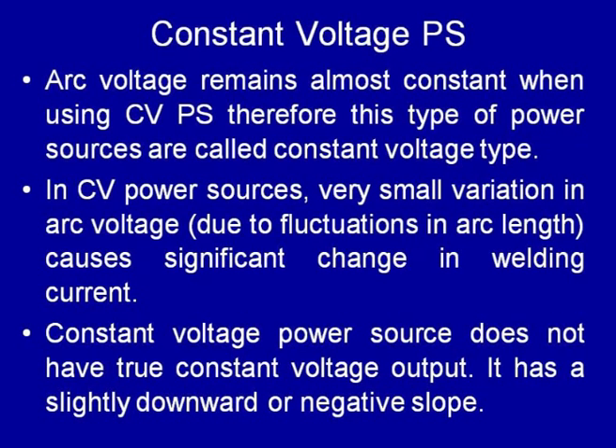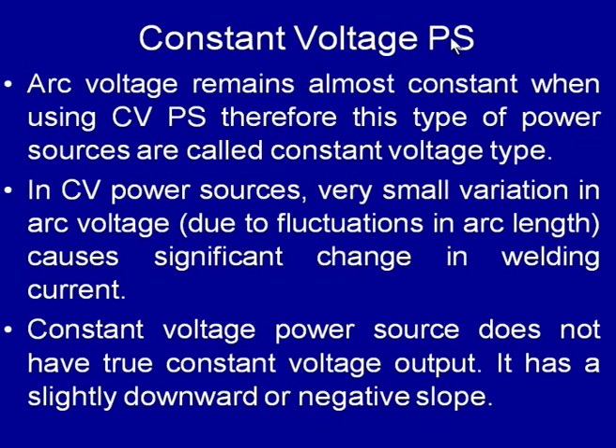In the case of constant voltage power sources, the arc voltage largely remains constant, and that is why this type of power source is called the constant voltage type. In the constant voltage type of power sources, a very small variation in arc voltage due to fluctuation in arc length causes a significant change in the welding current. This is just opposite to that of the constant current power sources. In the earlier case, a large change in the arc voltage was causing a small change in the welding current, while in this case a small variation in the arc voltage causes a significant change in the welding current. This aspect is exploited to have the self-regulating arc, so that arc length is maintained automatically during welding when using constant voltage power sources.